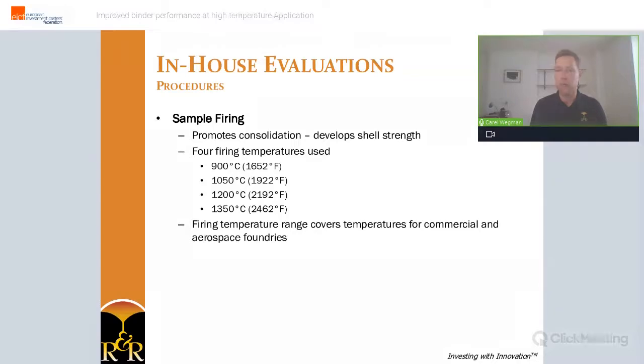Firing or pre-firing is obviously a very important process that promotes the consolidation of the shell structure. It develops the shell strength to sustain the stress exerted by metal during pouring. We chose 4 firing temperatures to look at the impact on strength for the 2 binders. We believe that the range of between 900 and 1350 degrees C is wide enough to cover typical shell temperatures for both commercial and aerospace applications. Test bars were fired at these temperatures for 1 hour and cooled prior to further testing.